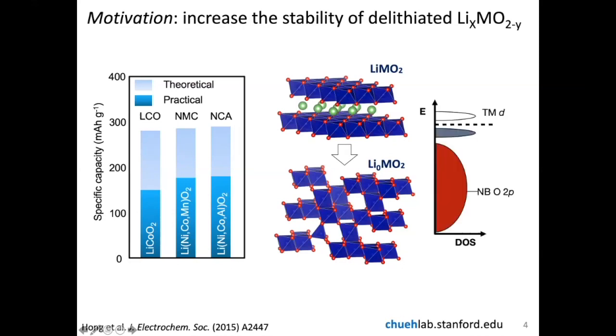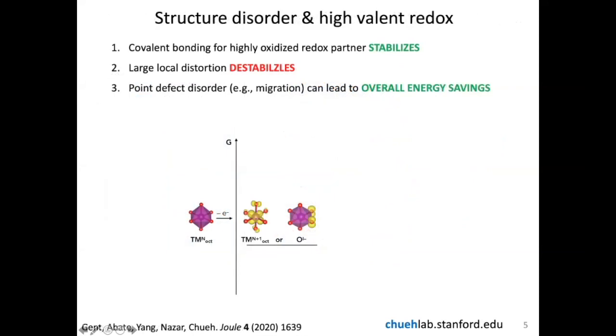And one of the reasons this happens is due to the electronic structure that Ram already highlighted. As you delithiate the material, you are oxidizing the material and lowering the Fermi level. And at some point, you're going to reach the non-bonding oxygen orbital. And this process can lead to oxygen evolution from the material and a wide range of other degradation processes. So I want to first talk about how to stabilize the material against oxygen evolving, and also talk about the link between oxidizing the material and the transition metals moving around.